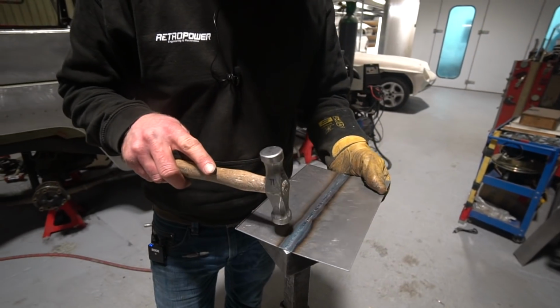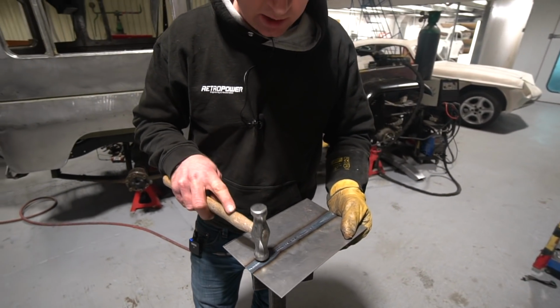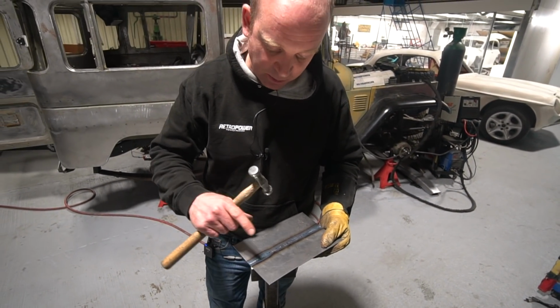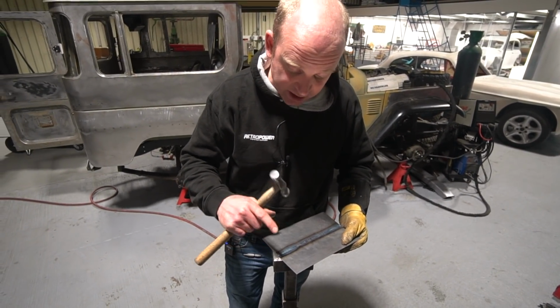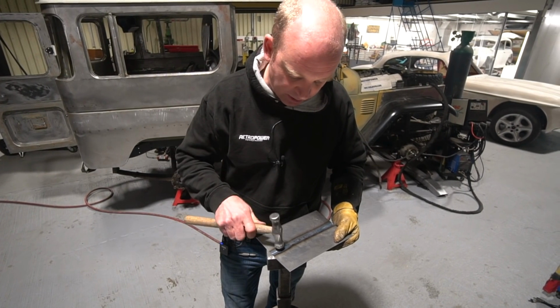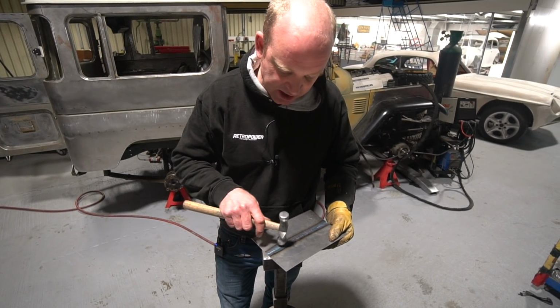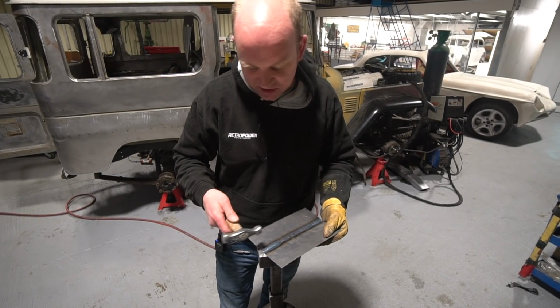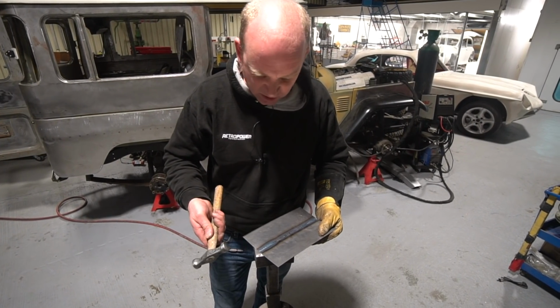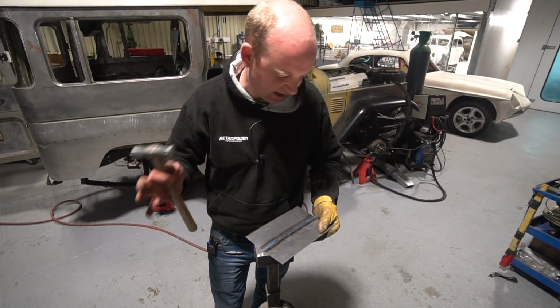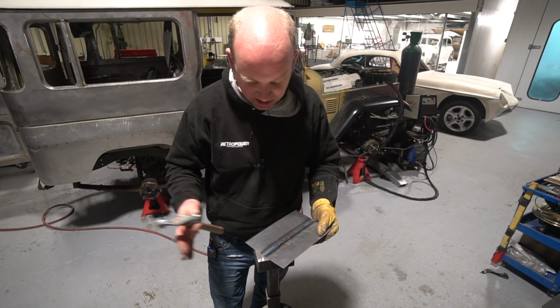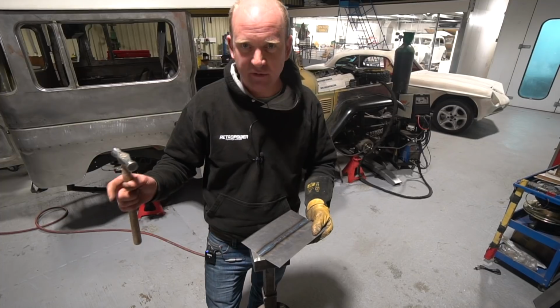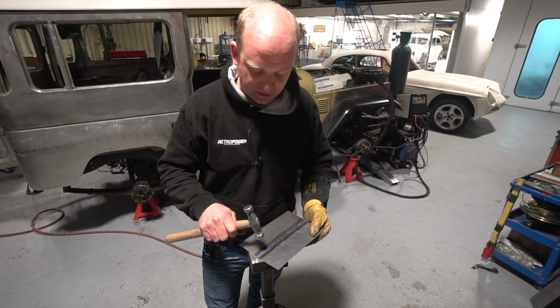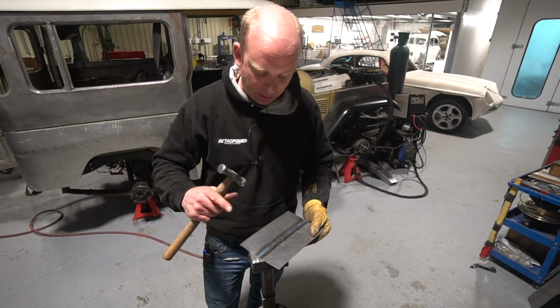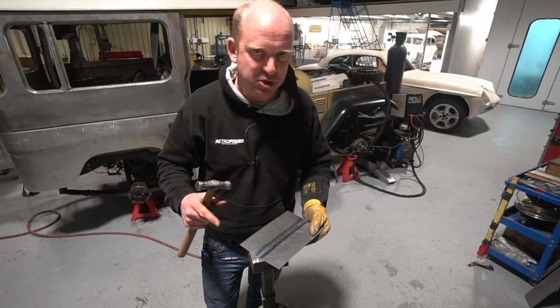The aim of the planishing is to, again, a little thing I didn't explain very well actually over there, I was talking about stretching the weld. The reason we need to stretch the weld is when you deposit metal, you're depositing the metal in the weld seam at the melting point, say 1400 degrees C, let's say. I mean, it may be more than that, it may be less than that, but let's say 1400 degrees C. Steel has a coefficient of expansion. So if you deposit it at 1400 degrees C, it will shrink by its coefficient of expansion back down to an ambient temperature.